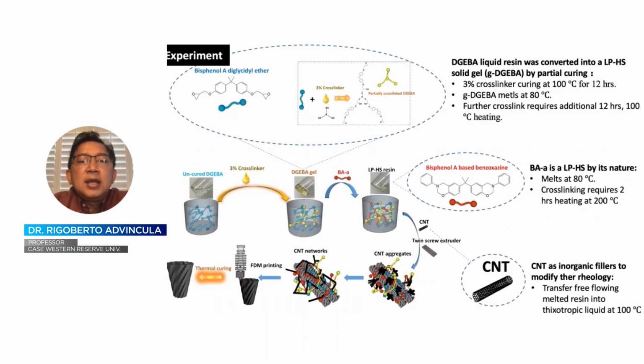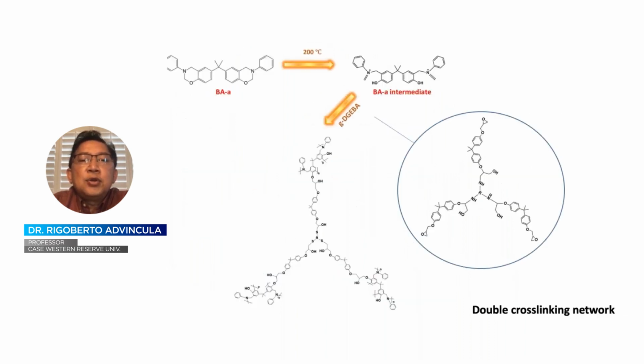Now, a key ingredient that we added on this benzoxazine and epoxy structure is actually carbon nanotube. Carbon nanotube here has several roles. It is useful for changing the viscosity of the material. And secondly, it's capable of adding electrical conductivity. And in this case too, it actually helped in the shape memory properties, as I will demonstrate to you soon. So the chemistry of the two materials are shown.